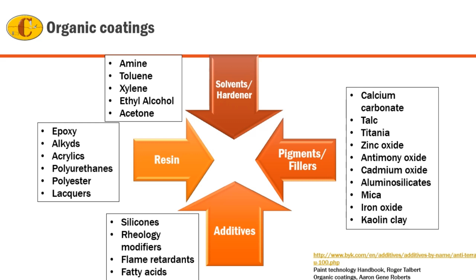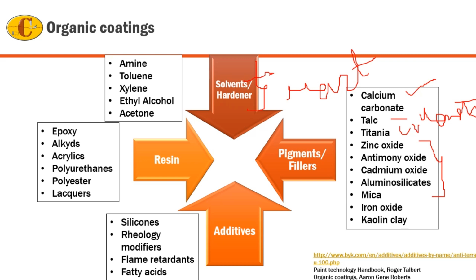The major components of organic coatings are resin, which makes up the main coating molecular part, solvents or hardeners. So solvent will be to dissolve the coating and paint it, or the hardener, which will react with the resin. In addition to this, depending on the application, you will have pigments or fillers. So to increase the mechanical strength, you may have calcium carbonate. To increase the density, you may have the talc. To have UV radiation resistance, you may have titania. You may have these to change the color of the coatings, especially in cars and automotives.